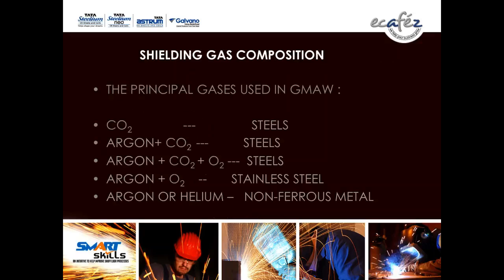Shielding gas composition, the principal gases used in the GMAW process. CO2 can be used for steel. Argon plus CO2 can be used for steel. Argon 80%, CO2 20%. If you want a higher quality weld, then use argon 82%, CO2 18%.